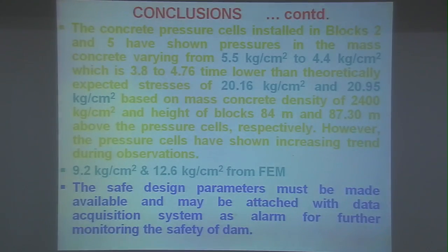I had this stress as 5.5 to 4.4 kg per centimeter square based on the height of the concrete over this instrument. And the only data I could get was from a FEM analysis done by IIT Roorkee, that stress from static analysis was 9.2 kg per centimeter square, from dynamic analysis was 12.6, but our stresses were within these limits. The safe design parameters must be made available and may be attached with the data acquisition system as alarm for further monitoring of the safety of the dam.